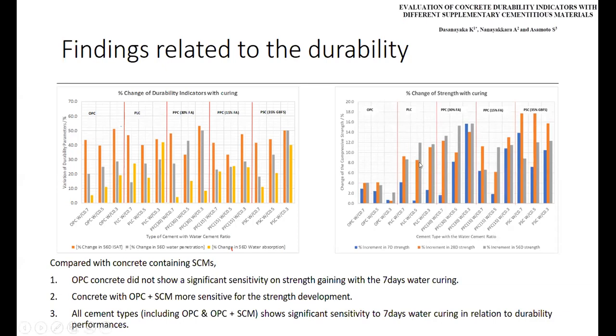So you can see here, OPC doesn't show a significant impact on the strength development with the curing, because OPC usually has a tendency to complete its hydration very quickly with its chemical composition, but the other materials have other mineral components, so it takes time. So if you are utilizing OPC, the strength gain will not be much impacted by water curing, but for OPC as well, you can clearly see the durability will improve drastically. So for whatever cement type, water curing or proper curing and reduction of water cement ratios are very important if we want to get higher strength and higher durability.